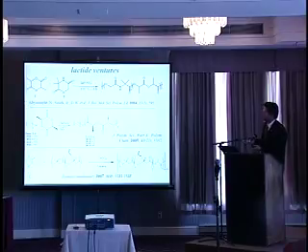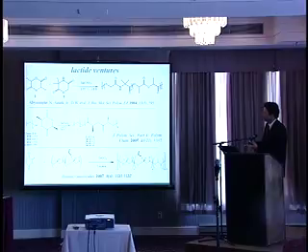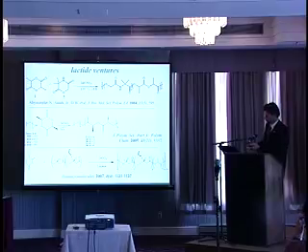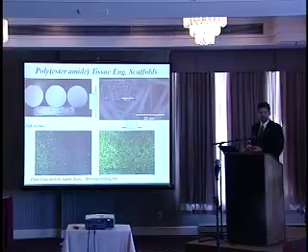Some lactide ventures, just to show, I work with bioengineers and other people to try to tune the affinity of these bioabsorbable materials and to cells, to different cells. So we look at lots of different types of copolymers. We try to use commercial materials. These are commercial oligoethylene alcohols. And we also look at these bacteria-produced polyhydroxyalkanoates, which are also commercial biometabolics. So this just shows a little bit of the cell studies. By comonomer incorporation, we can do electrospinning to get much more surface area, and then we can tune cell affinities by changing just the comonomer relationship just a little bit.